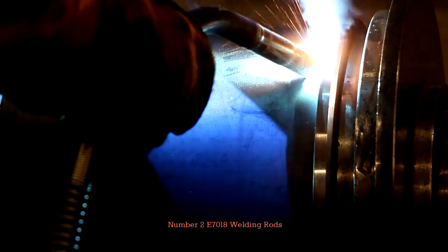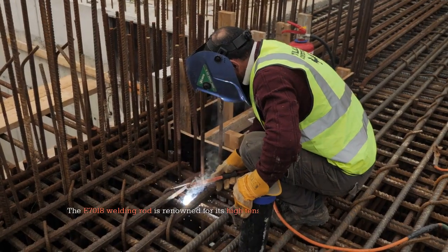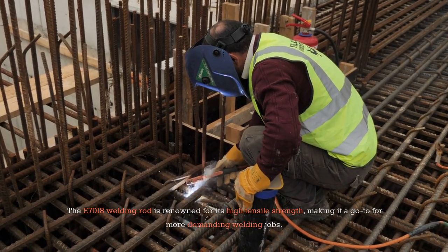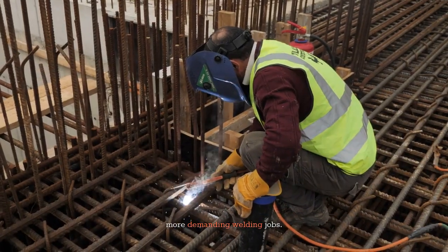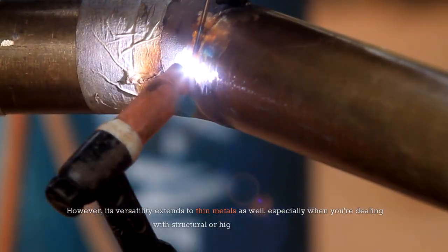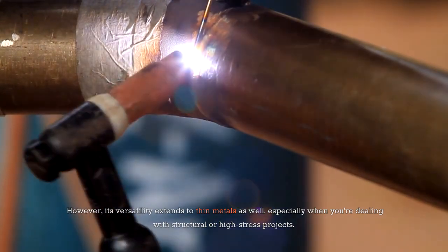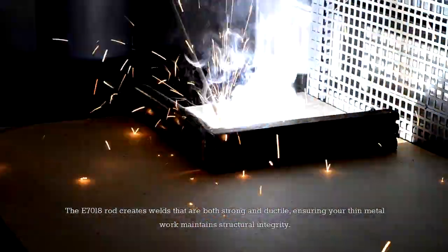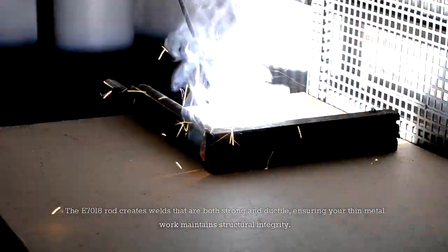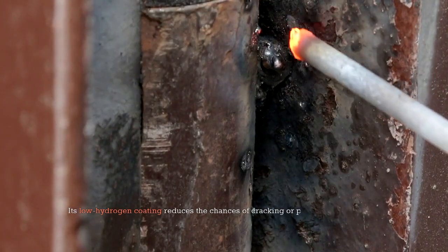Number 2. E7018 Welding Rods. The E7018 welding rod is renowned for its high tensile strength, making it a go-to for more demanding welding jobs. However, its versatility extends to thin metals as well, especially when you're dealing with structural or high-stress projects. The E7018 rod creates welds that are both strong and ductile, ensuring your thin metal work maintains structural integrity. Its low hydrogen coating reduces the chances of cracking or porosity in your welds, which is especially important when working with thin materials. Though it's best used with a DC power source, it can also be utilized with AC, offering flexibility based on your equipment setup.